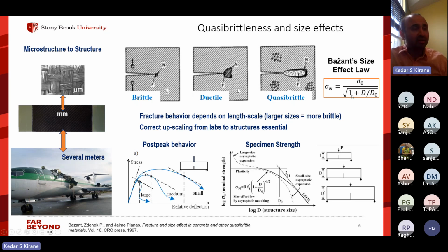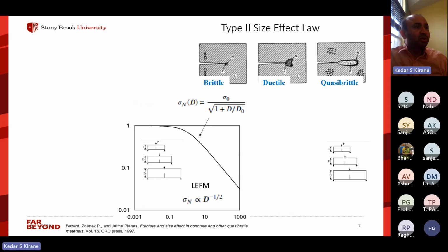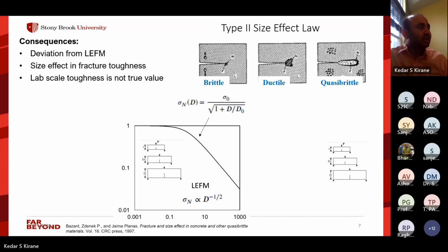So understanding the size effect is really, really important for most materials, including composites. Now, a little bit more about this size effect law. This is basically how the size effect law looks, where the strength decreases with size, and in this intermediate region, a length scale has to be introduced. It is not self-similar. And then at very large sizes, it becomes what LEFM, or linear elastic fracture mechanics, describes. Now, an important consequence of this is that if you are in this region, where the x-axis is size D, if you are somewhere here, and if you test the specimen in the lab for fracture toughness, you will actually see that the fracture toughness becomes size dependent, or it appears to be size dependent.